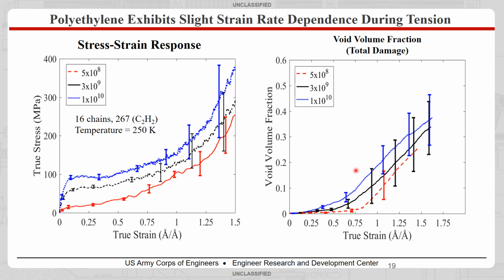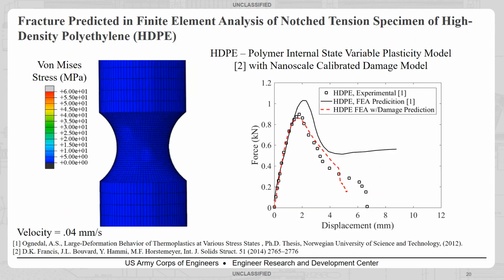So it's slightly strain rate dependent, but there's not a huge disparity in strain rate in this, as we see like in the yield curves. So we are able to capture at different strain rates very similar void volume fraction evolutions, which all match the experimental results that we saw earlier. So then we use the calibrated nanoscale damage model and this internal state variable plasticity model to predict fracture in this notch tensile specimen that we have here.